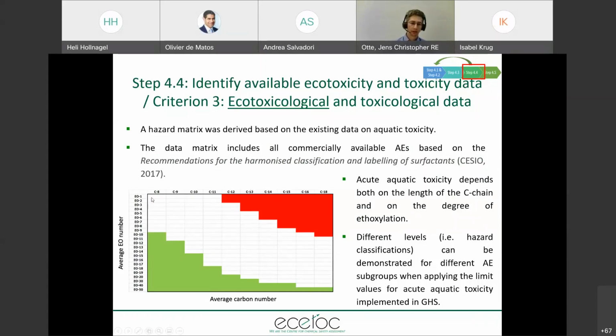And you can see that dependent on the C chain length and the ethoxylation degree, that again corresponds to the hydrophobicity, we can put in certain threshold values, or at least assign certain areas with high toxicity, moderate toxicity in the white area, and low to absent toxicity in the green area. So acute tox for aquatic depends both on the chain length and the degree of ethoxylation. And we can bring these into different subgroups when applying the limit values for acute aquatic toxicity implemented in GHS.